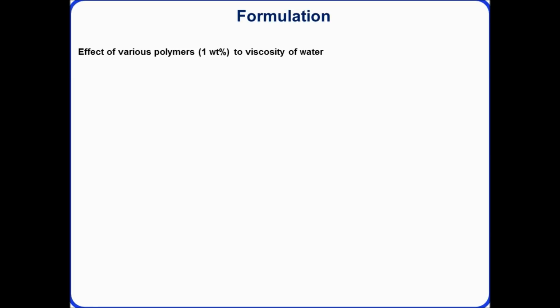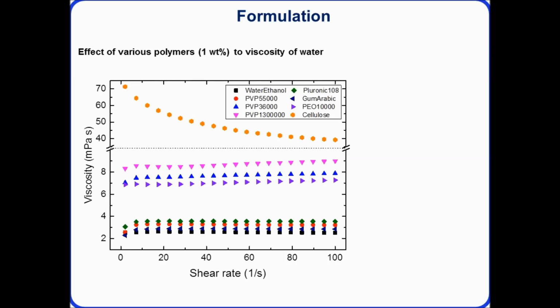So we do lots of formulations. If we want to make a conductive ink, we don't want to add too much material which is insulating. So lots of these polymers that can help improve viscosity are having a negative effect on the resulting conductivity. So we want to add a polymer which has the lowest weight percentage loading but can give the highest improvement in viscosity. So just screening many different polymers.